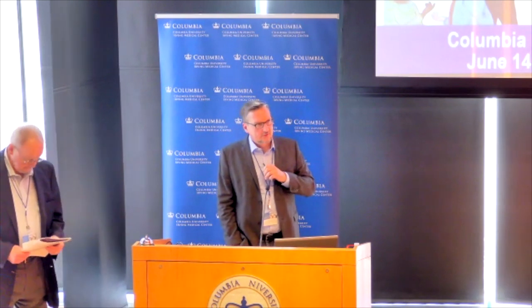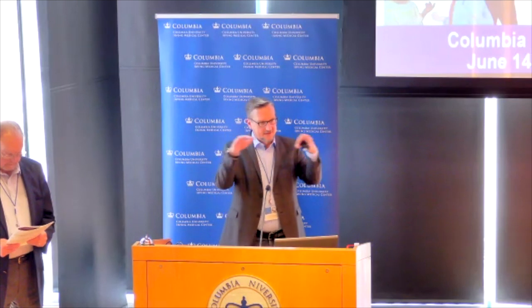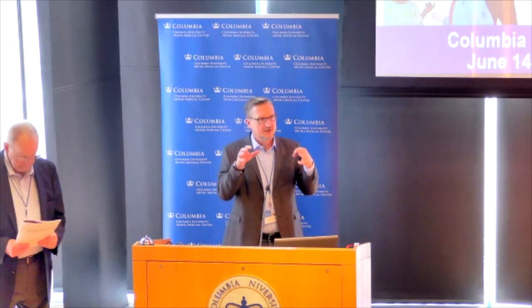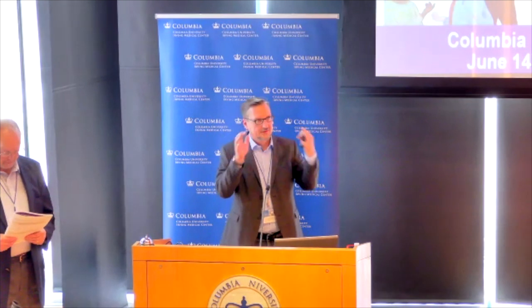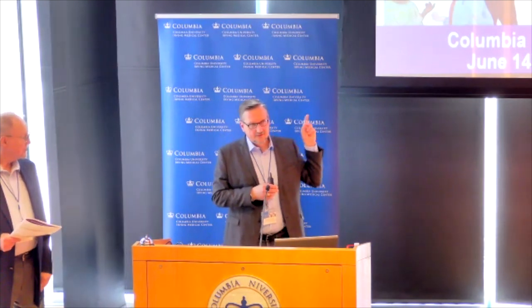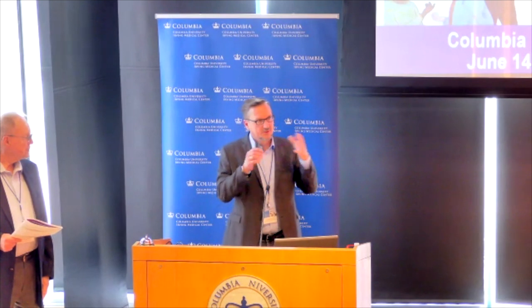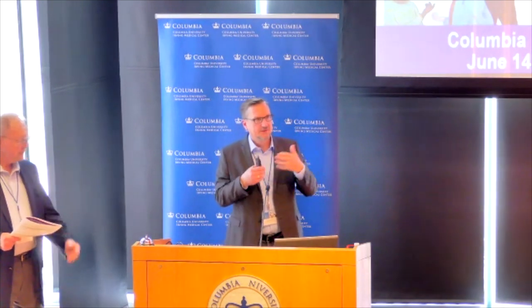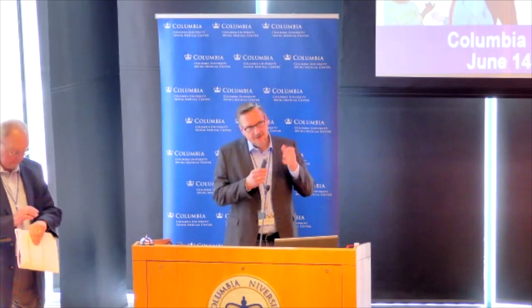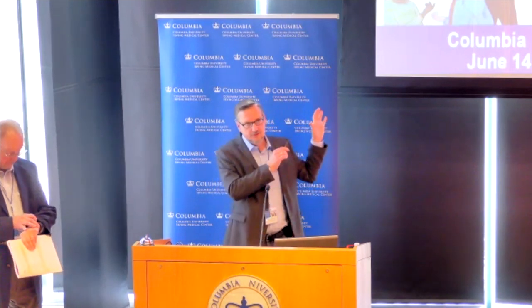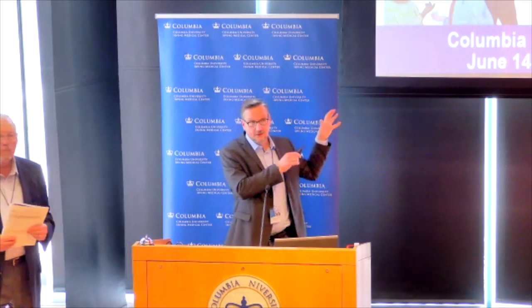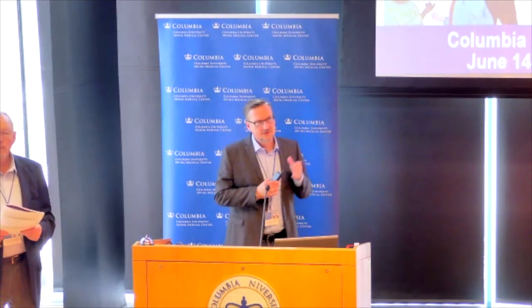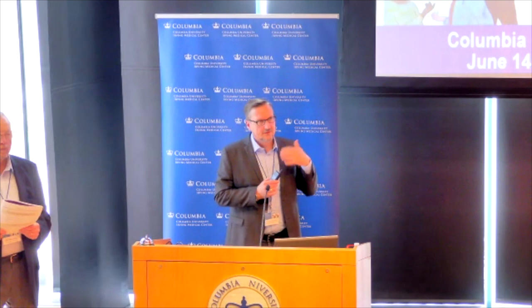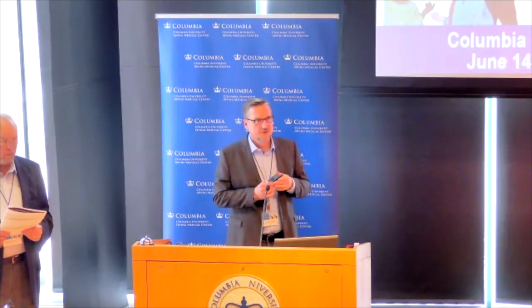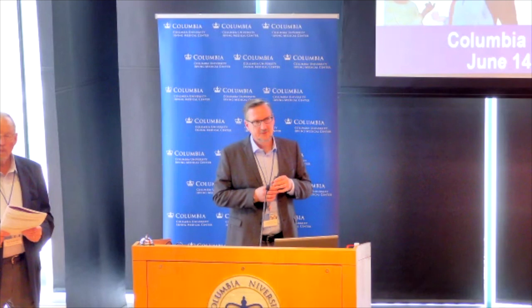Light extraction is going to be the toughest one because normally you use a silicone encapsulant for light extraction. All the blue and white LEDs have this encapsulant. At such high photon energies, the problem is that most organic encapsulants do not hold up. So finding something that you can use, or maybe using a totally different approach like these micropixels, might solve the problem. So I don't think there's a fundamental limit. It's just a very hard engineering problem. Yeah. Okay, it's just time. Time and manpower, yeah.